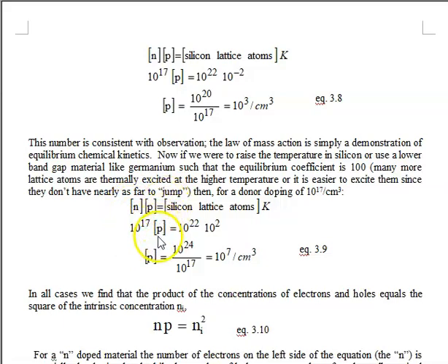We want to find P. The number of silicon lattice is still 10 to 22. That hasn't changed. But the K, instead of being 0.01, is now 100. And now we have P is 10 to the 7th. So at an elevated temperature, it only depends on the temperature, the law of mass action can be quite different.